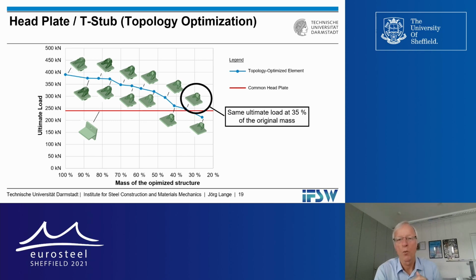And this leads to a tremendous optimization and a tremendous reduction in the material. If you look at this graph, you see on the left-hand side, if we use as much material as we use for the head plate, we get approximately 50% more ultimate load, nearly 50%. And if we reduce the mass, somewhere in the area of 35% of the original mass, we get the ultimate load that the common head plate has. So it's a large reduction in material, and that's good looking from the printing part, because as I said very early in the presentation, we print up to 10 kilograms per hour. In average, in small structures, as we see it here, we come closer to 4 or 5 kilograms per hour.